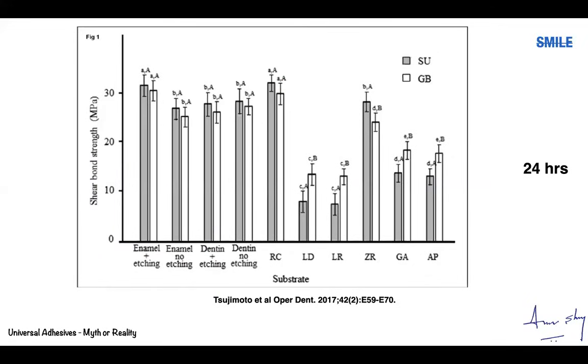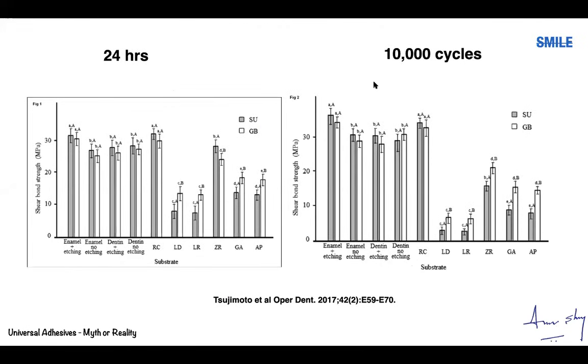Last but not the least, please understand one thing, that all bonds fail over time. And if you don't do the job properly, your failure is going to be higher. So if you compare 24 hours and after 10,000 cycles, if you look at bonding to enamel and dentine, it is more or less similar. But if you look at bonding to lithium disilicate here, can you see these bond strengths fall off very rapidly after 10,000 cycles of thermocycling? That means after use, the bond strength tends to be lower. I showed this slide for a particular reason.